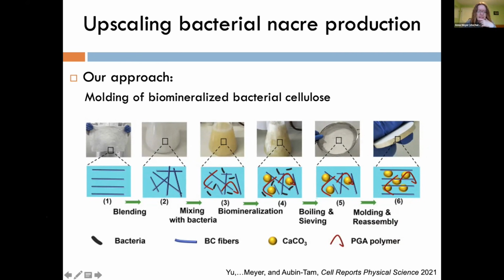But the cellulose is so hydrophobic that you can't mineralize it with calcium carbonate. We kind of bounced off this project several times, where if you just take this cellulose and put it with the bacteria that make the calcium carbonate crystals, it's so hydrophobic that the solution making the crystals doesn't penetrate into the cellulose. So you end up with just your chicken breast of cellulose with crystals on all the outside surfaces, but not inside. So that's not what we're going for.